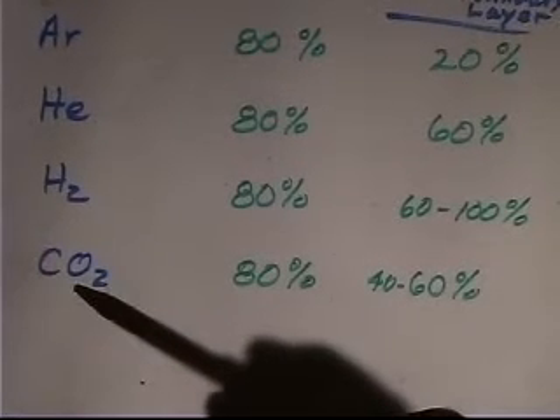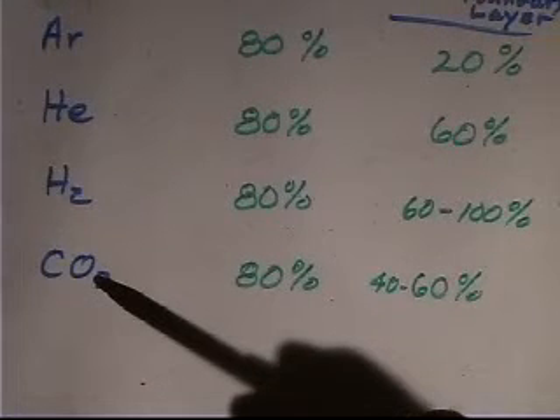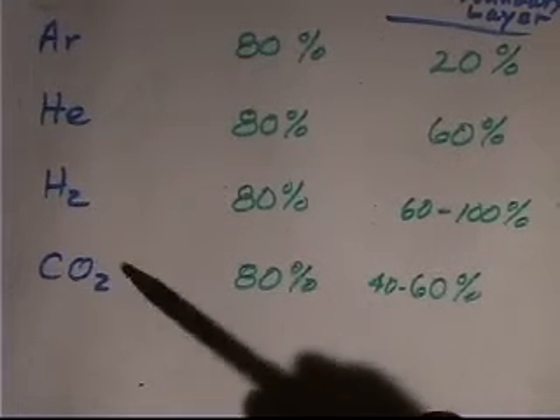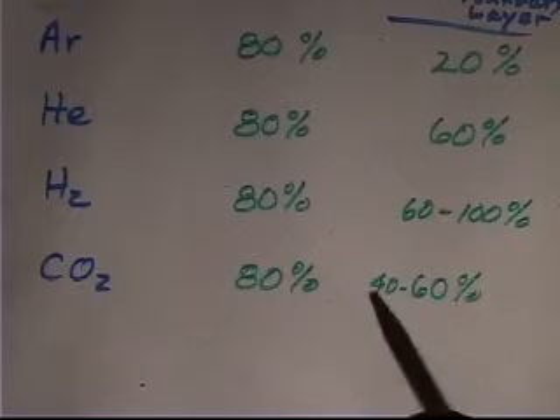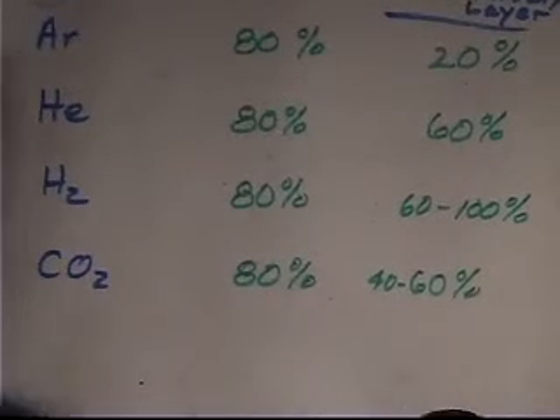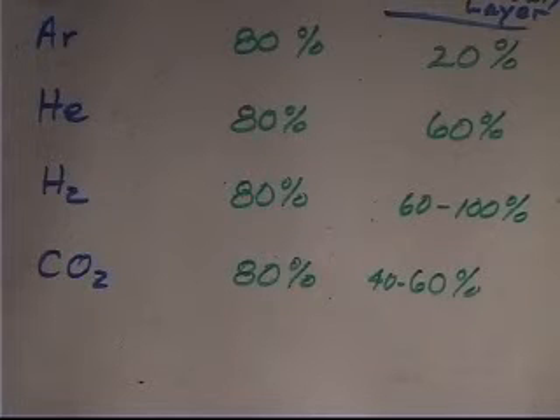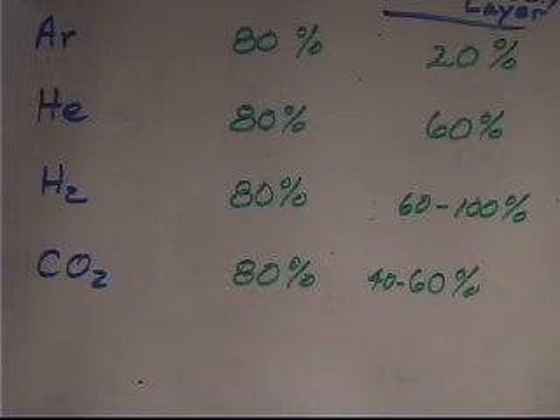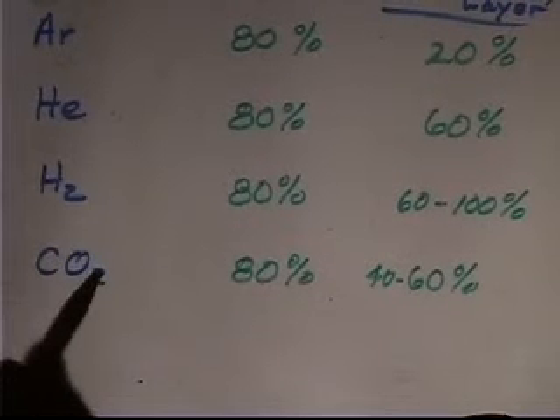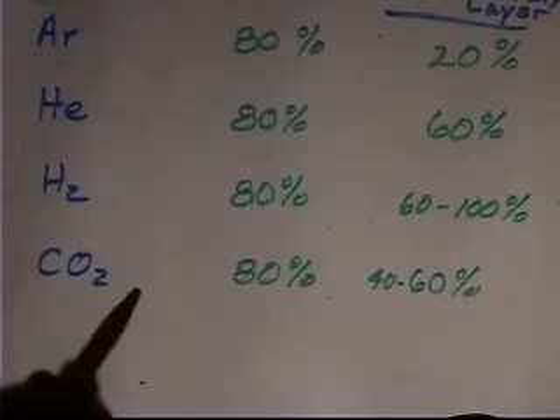If I use CO2, well, this is pretty heavy. That's 12 plus 32, that's 44 as a molecular weight of CO2. But it turns out it gives you a higher heat transfer. In this case, and actually with hydrogen as well, there's something called the reactive thermal conductivity. Up here in the plasma, the energy in the plasma is going to cause that diatomic or triatomic gas to dissociate. So I don't have H2, I have 2H, two hydrogen atoms as opposed to a hydrogen molecule. Or I have carbon monoxide plus a monatomic oxygen, when CO2 dissociates into CO plus oxygen.